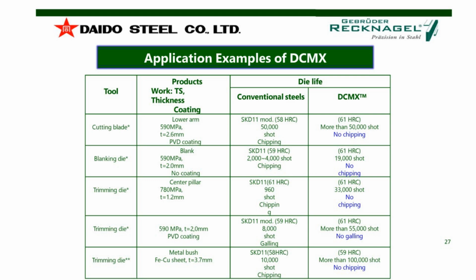And then he moved to DCMX. The hardness was always a little bit higher, but the results were always better. In the first line, he had no chipping. For the blanking die, he had with D2 grade a tool lifetime of 2,000 to 4,000 shots, and with DCMX he had 19,000 cycles. Impressive result, and the next results are also very impressive. The trimming die in the middle for the center pillar: with D2 he had just 960 shots, and with DCMX the tool lifetime goes up to 33,000 cycles.